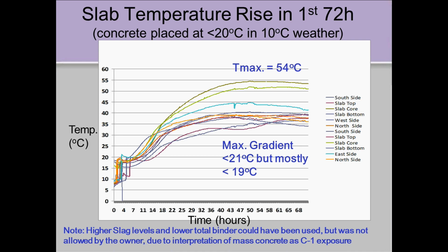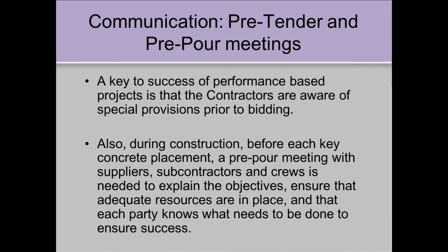We could have used higher slag contents in that mix. They only used 50%. They could have used lower total binders to meet the requirements, but the owner we couldn't convince the owner because he interpreted the whole mass concrete as a chloride frost exposure, as opposed to the outer layer that was going to be added later. And so we had some issues with that.